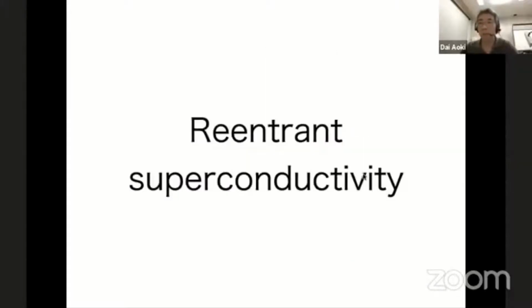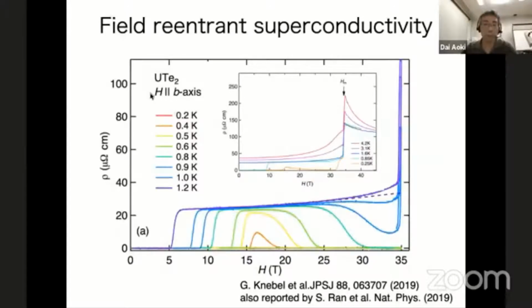Okay, so now I want to go to the reentrant superconductivity. Here we measure the magnetoresistance along the b-axis. The b-axis is the hard magnetization axis. So you can see clearly the reentrant superconductivity. For example, at 0.2 Kelvin, the lowest temperature, the magnetoresistance is always 0 up to 35 Tesla. However, increasing the temperature, for example at 0.6 Kelvin, it shows the normal state.